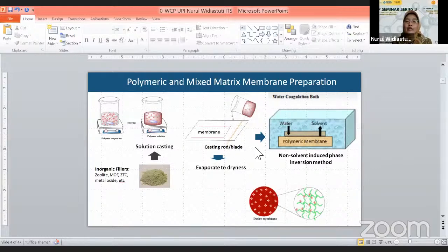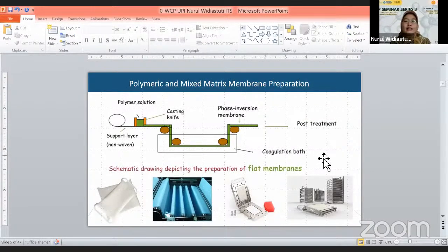And also, if we prefer to use the non-solvent induced phase inversion methods, then this polymer solution can be immersed in the water coagulation bath. Then we can create the membranes. And here are examples of flat sheet membranes.